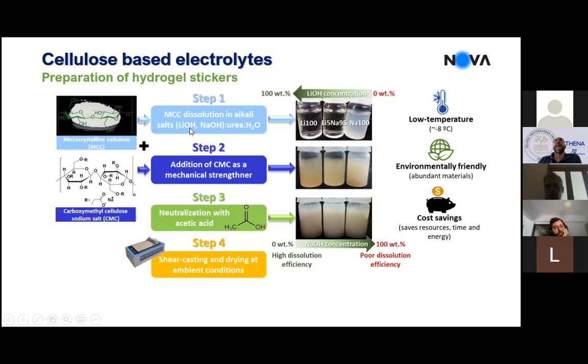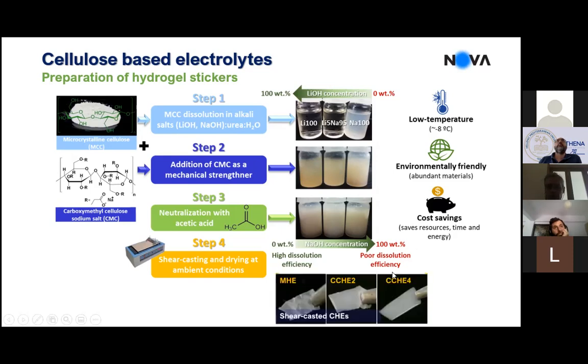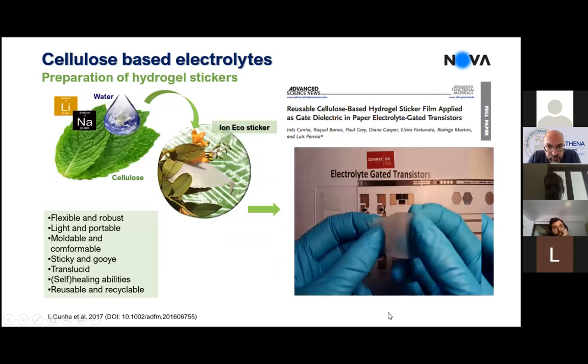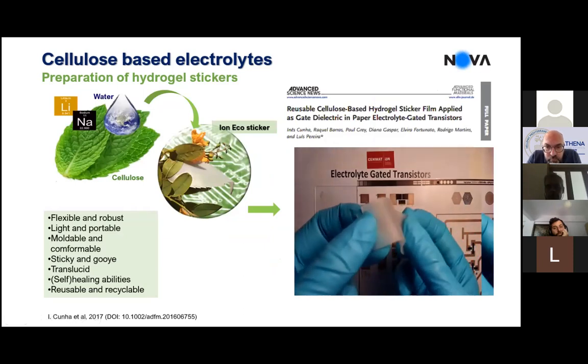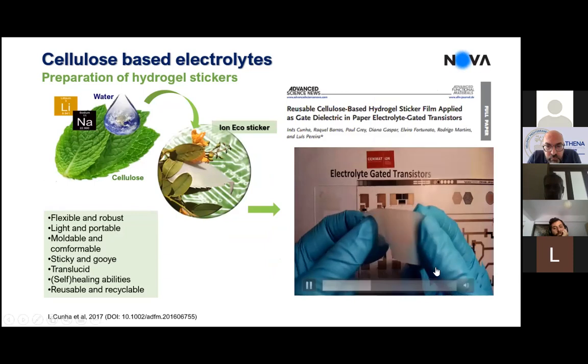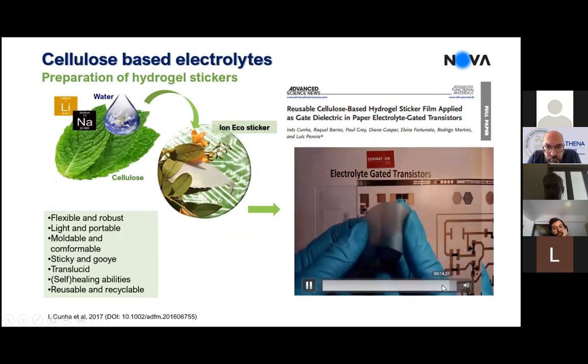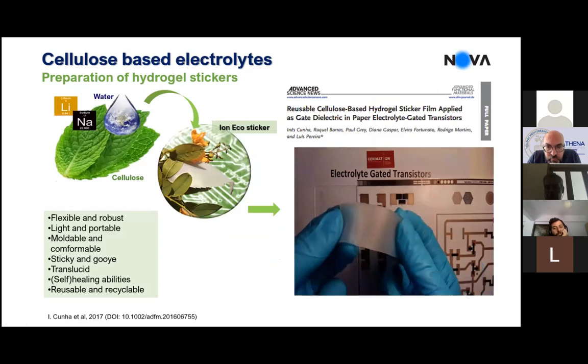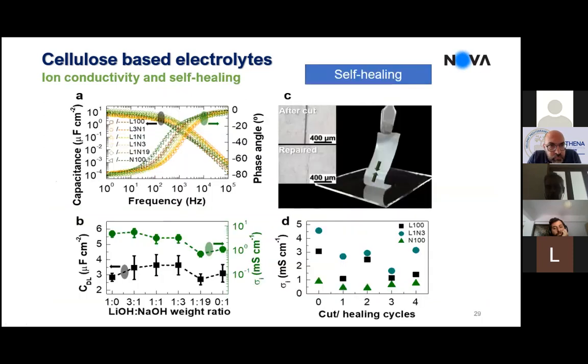Okay, so we are replacing lithium with sodium hydroxide, but we cannot replace 100% because the dissolution is not perfect under 100% sodium hydroxide. But we can go up to a mixture of 95% sodium hydroxide and 5% lithium hydroxide. And so you can make this type of membranes by optimizing the composition, and of course getting good flexible membranes, as you see here, electrolytic membranes that are kind of sticky. So we can cut and put them over the transistors and they behave like a dielectric. So it's a pretty simple way to create the dielectric layer on these transistors.